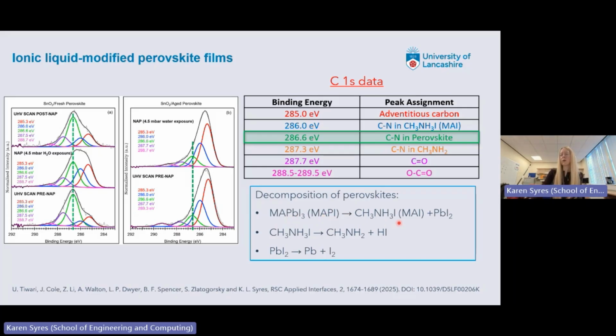So here's some more chemistry for anybody who likes a bit of chemistry. It decomposes, and the lead from the actual perovskite structure ends up coming out of that structure and forming lead iodide. And then both of these products can go on to degrade further, and you can actually get degradation all the way to metallic lead. So a lot of these other peaks, particularly in the aged one, are due to the decomposition products. This one that's a week old is already quite heavily decomposed.